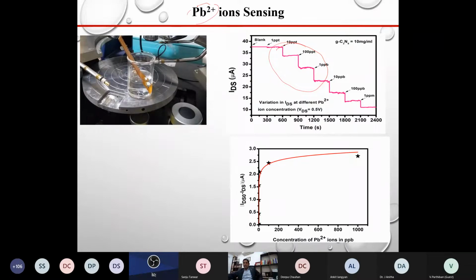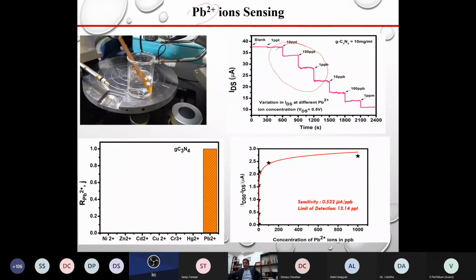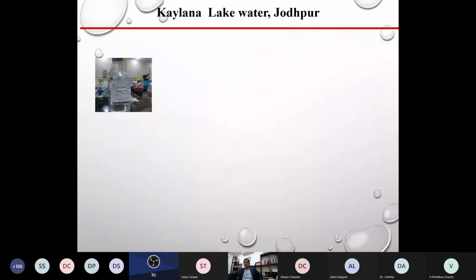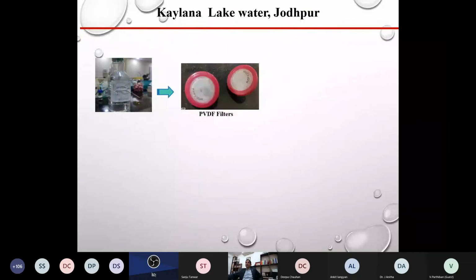Here you can see the sensitivity is very good in this case, around 0.532 microampere per ppb. And if you see the selectivity, it is highly selective to the lead ion; we have not received any response from the other ions. So by using this graphitic carbon nitride, we can make highly selective lead ion sensors.